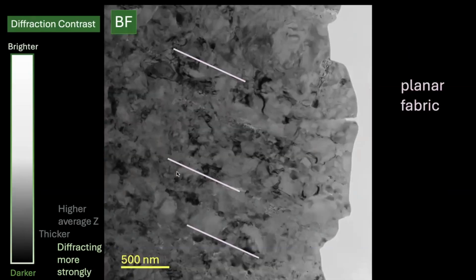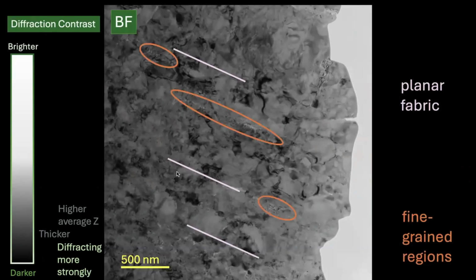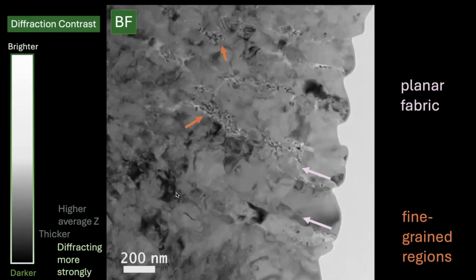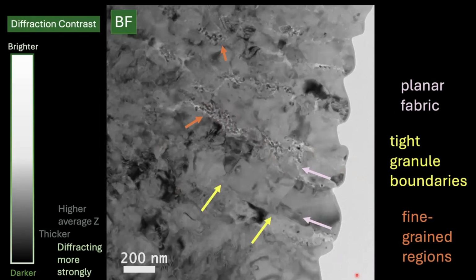Then that planar fabric, you can see it a lot better here. It's kind of northwest, southeast. So we also have those fine-grained regions, and they're kind of between the granules. So planar fabric, that's our second piece of evidence we'll use. And then here's kind of a zoom in on some of those finer grained regions. And you can see some tight granule boundaries, which is interesting. So third piece of evidence, tight granule boundaries.